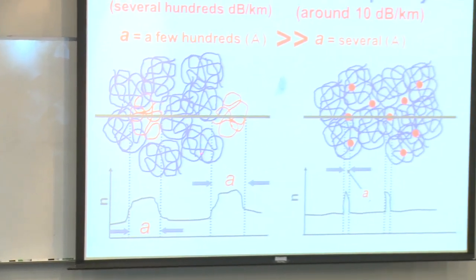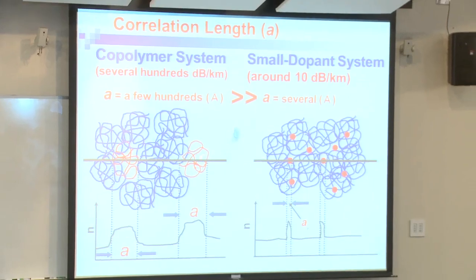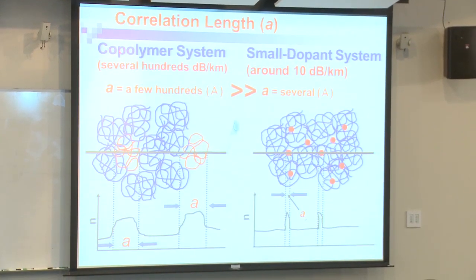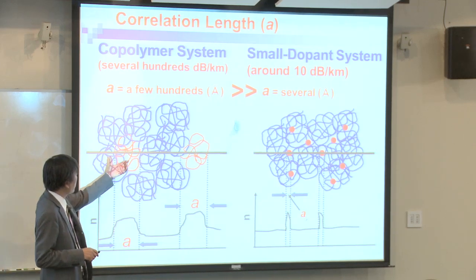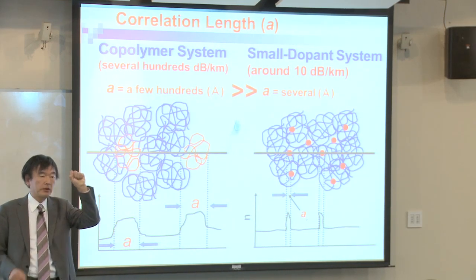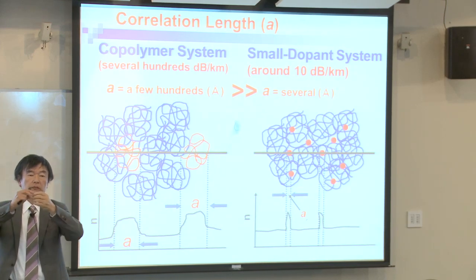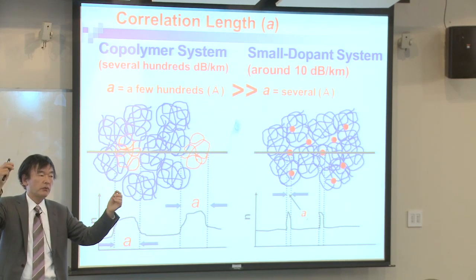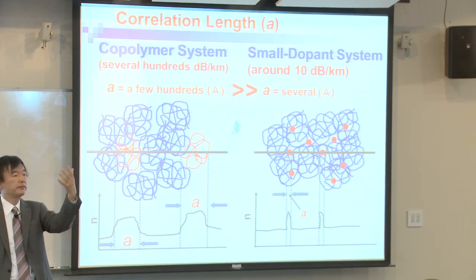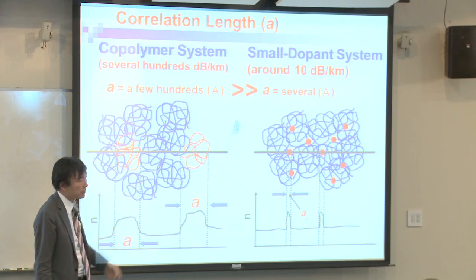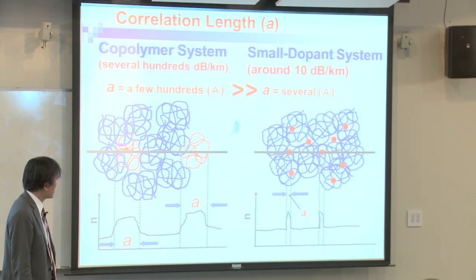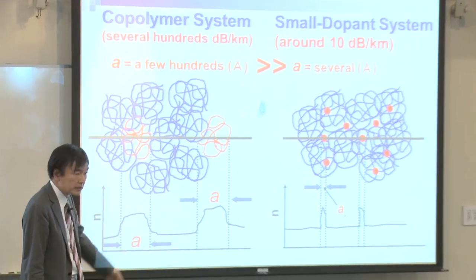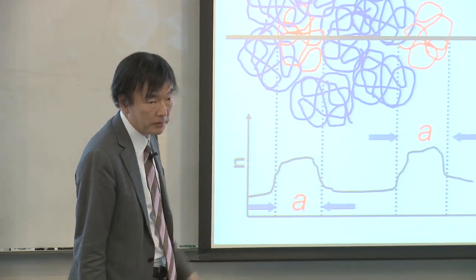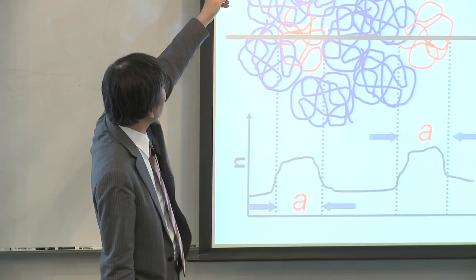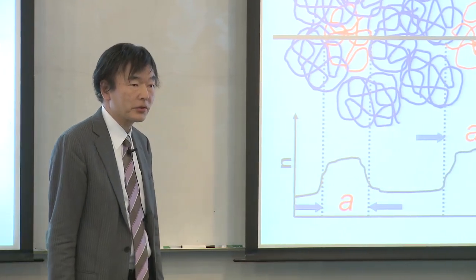Now, by deriving this equation, I came to the conclusion that I should stop the research. So far, I tried to make the index profile by changing the copolymer compositions. In the case of the copolymer, the minimum size of the heterogeneity is one polymer coil. Polymer is a very long molecule, and usually one molecule is just like a coil. And the size of this is a few hundred angstroms at least. If this size as the correlation length is inserted into the equation of Debye scattering theory, it easily comes to several hundred decibels per kilometer.